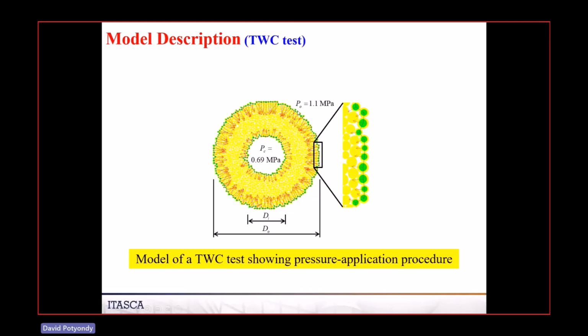We did this by applying pressure on this thing by using this algorithm whereby we find the particles on the surface, we conceptually construct a chain, and based on the pressure and based on the local orientation of this chain, we can apply an external force to those particles.